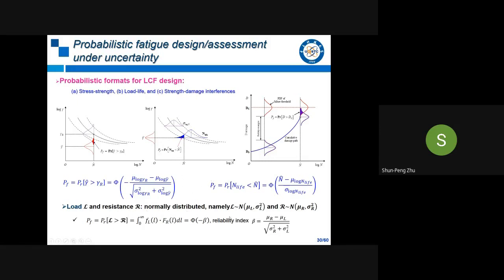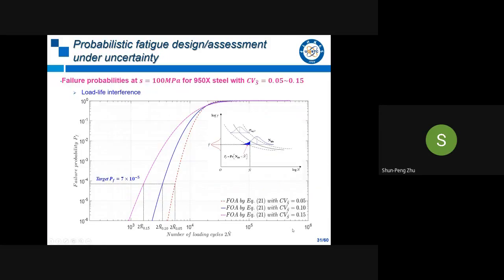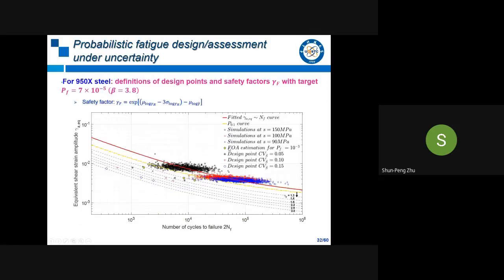And here, we use a normal distribution for the load and resistance, or stress and strength. With the failure probability, we can do this calculation. Here, beta is a reliability index, which can be quantified by the mean value and the standard deviation. And for the first material, based on the load-life interference, for the target failure probability of 7 times 10 to the minus 5, we can locate the design life at different load variations based on this mechanism. And here is for the final purpose.